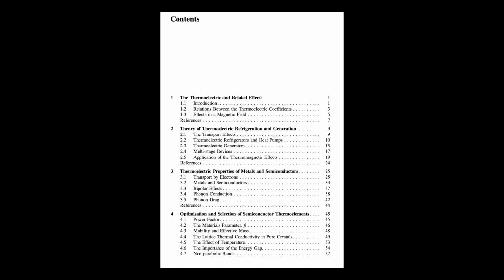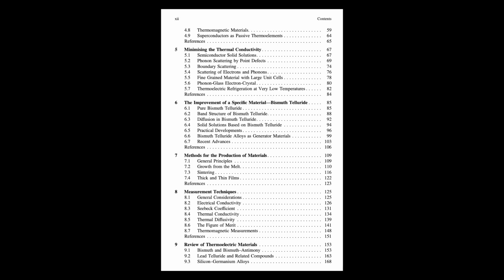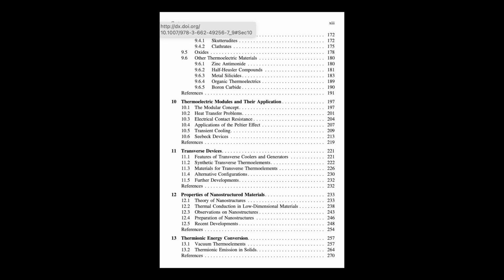And nanostructuring these helps. How does shrinking things down improve them? Nanostructure, making features on the nanometer scale, can be a huge help, especially for reducing lattice thermal conductivity. In things like PbTe alloys, adding nanoparticles, making nanowires, or creating layered superlattices introduces tons of interfaces. These interfaces scatter phonons really well, blocking heat flow. If done right, you can do this without hurting electron flow too much. So you lower lambda, keep sigma high, boost ZT. Examples include adding nanoparticles to alloys or creating nanostructures within PbTe itself.